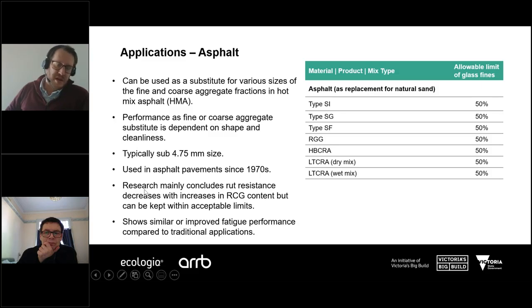We need to bear in mind its shape. It's important to be crushing it to gain a fairly homogeneous shape for our crushed glass, which is again one of the reasons why we're typically crushing to 4.75mm or below. So if you were to consider, say, the wall of a glass jar, typically that might be in the region of 5mm thickness. Therefore, if we crush our product to below that size, we get fairly homogeneous size dimensions in all directions, and that's particularly important. We don't want to have flaky particle shapes, because those can then be detrimental to the resultant properties of the asphalt mixture.